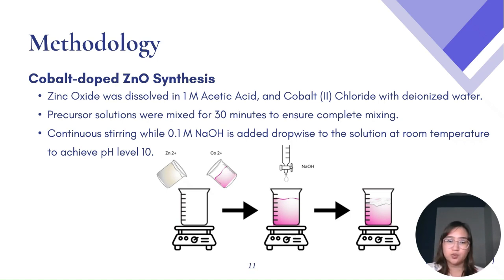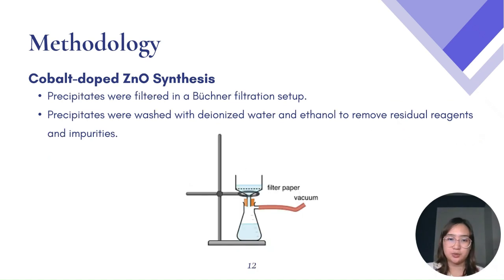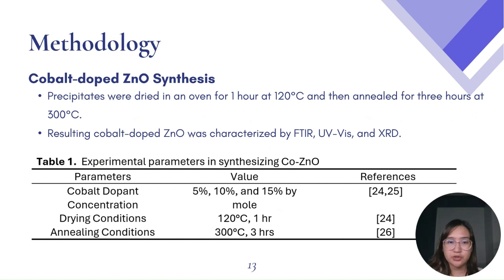The precursor solutions were mixed for 30 minutes to ensure complete mixing and then continuously stirred, while 0.1 M sodium hydroxide was added dropwise to achieve a pH level of 10. The precipitates formed were filtered in a Buchner filtration setup and then washed with deionized water and ethanol to remove residual reagents and impurities. The filtered precipitates were then dried in an oven for 1 hour at 120 degrees Celsius and then annealed for 3 hours at 300 degrees Celsius. The synthesized photocatalysts were then characterized by FTIR, UV-Vis, and XRD.